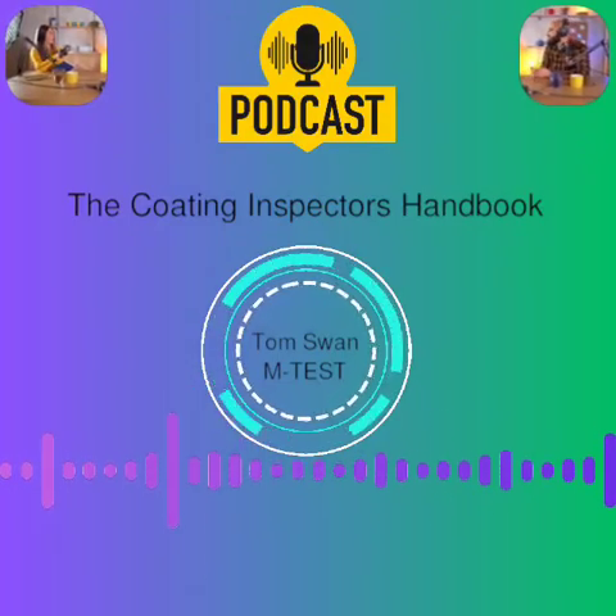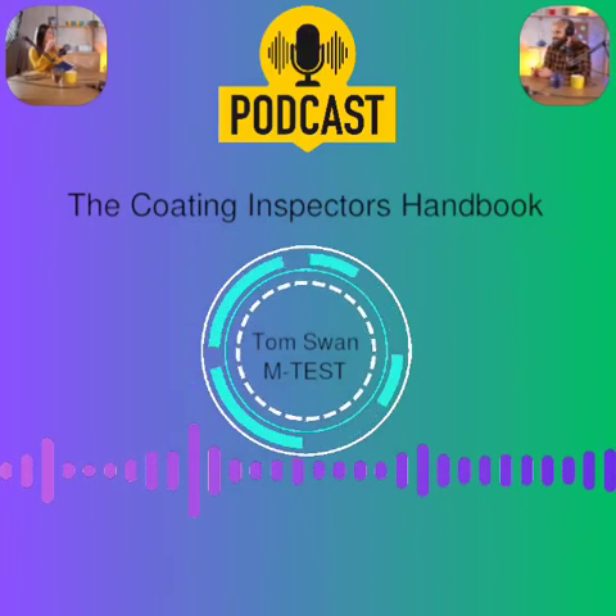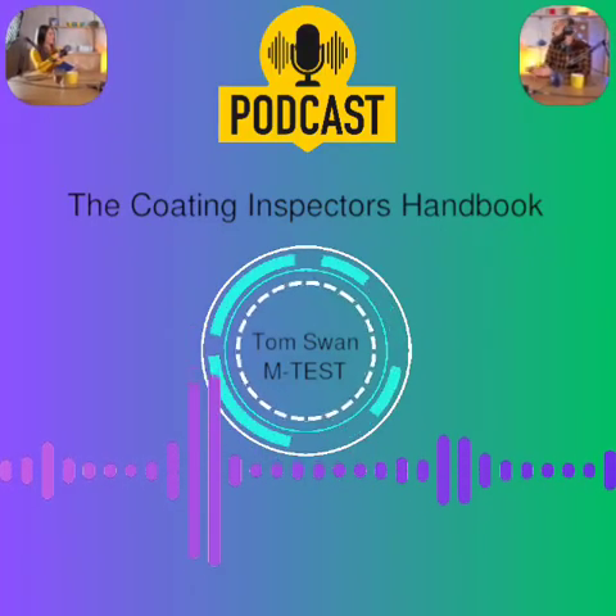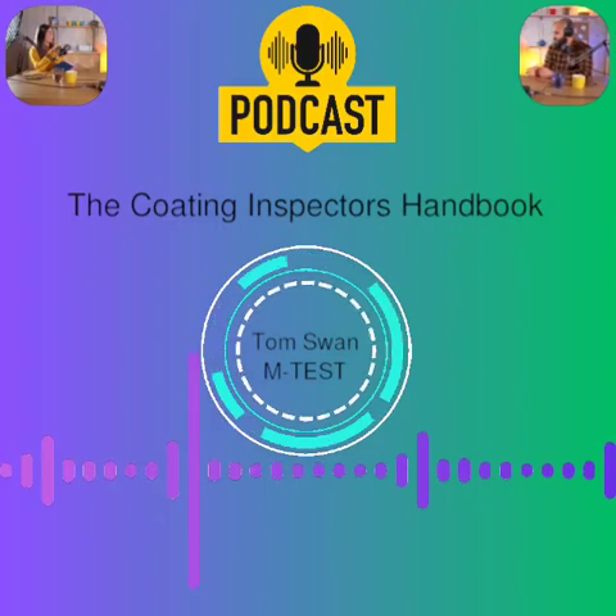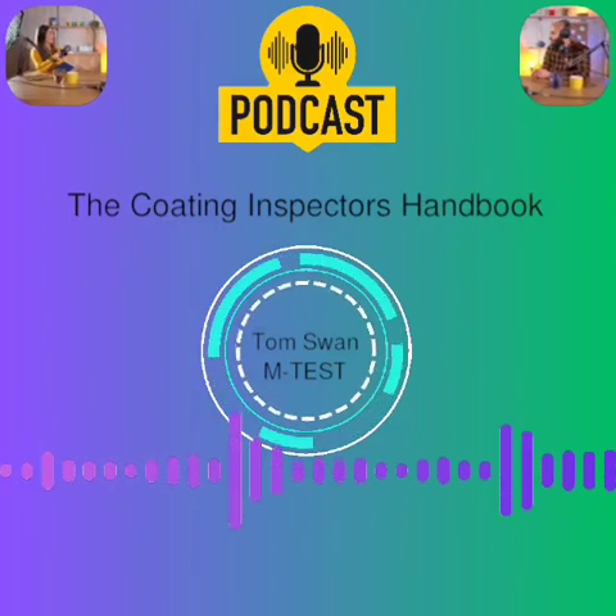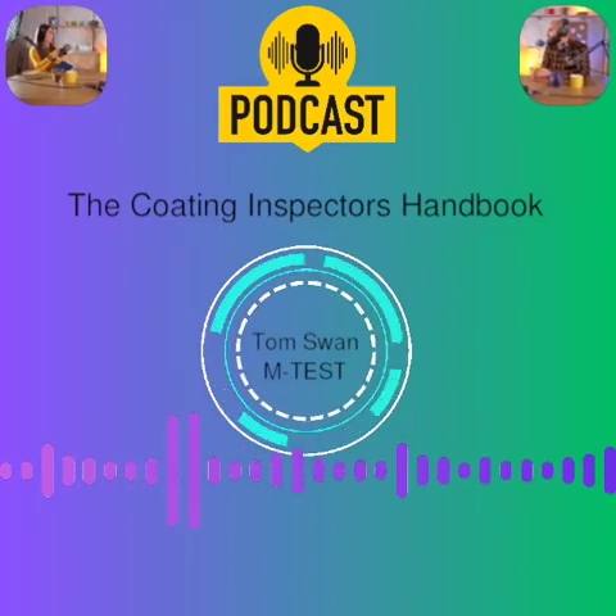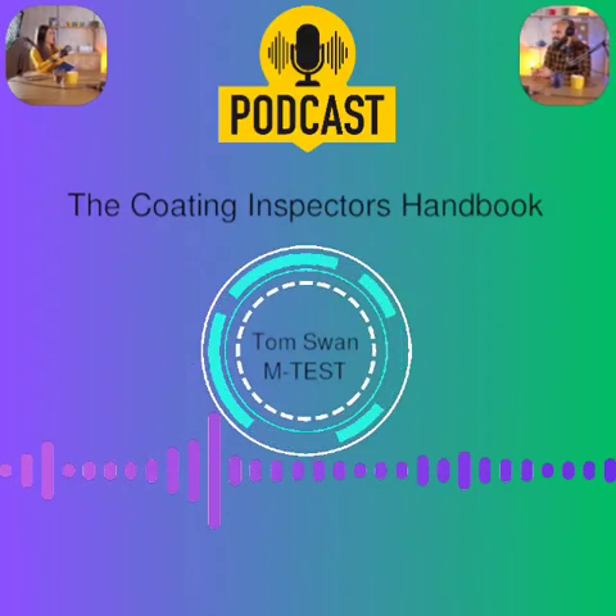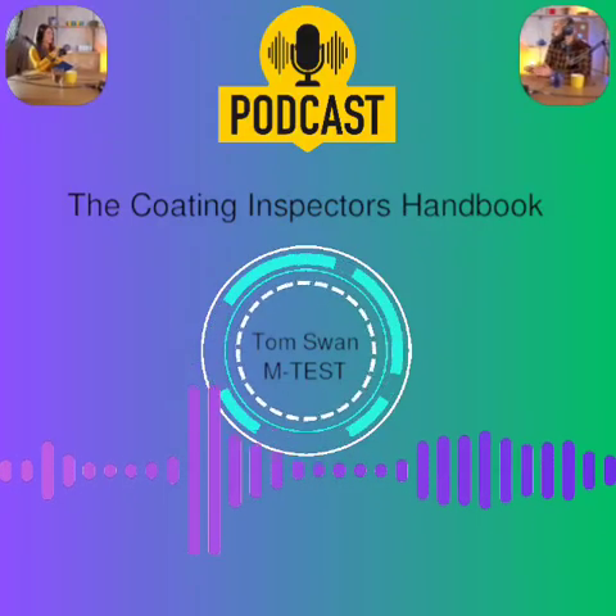Using the wrong thinner, wrong amount of thinner, wrong mix ratio for 2-part paints, not letting it induct or sit long enough after mixing, going past the pot life. All can cause problems. Big problems. Improper cure, poor adhesion, reduced life. You have to read and follow that PDS exactly.